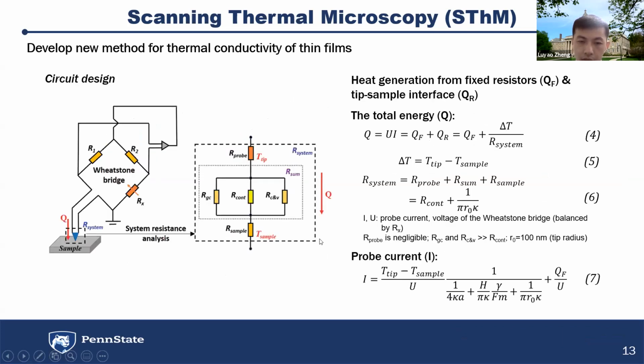And then we can set up a circuit to measure this thermal contact resistance. We use this setup with some fixed thermal resistors, and we apply some voltage and maintain a temperature difference between the tip and the sample. And we can address this equation: the total energy equals the heat generation of the fixed resistors plus the heat from the temperature difference between the sample and the tip. We can address our system through this equation, the sum of the contact resistance and also the resistance of the sample.